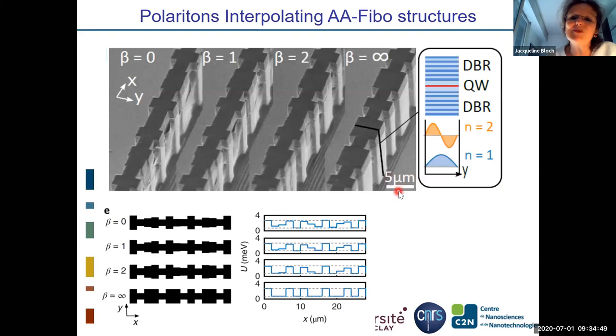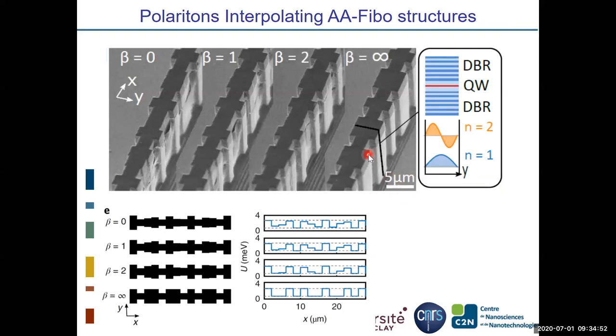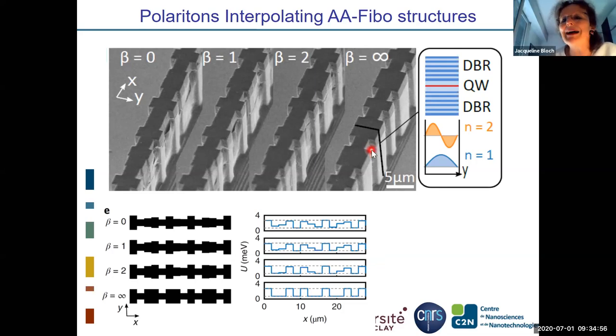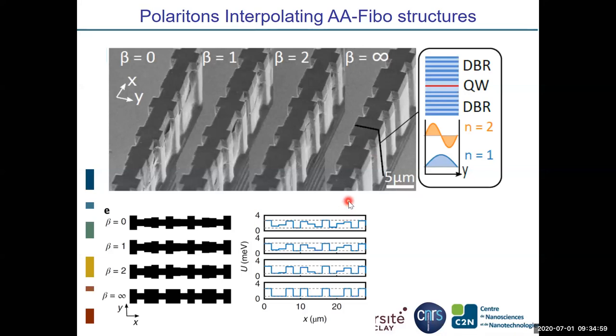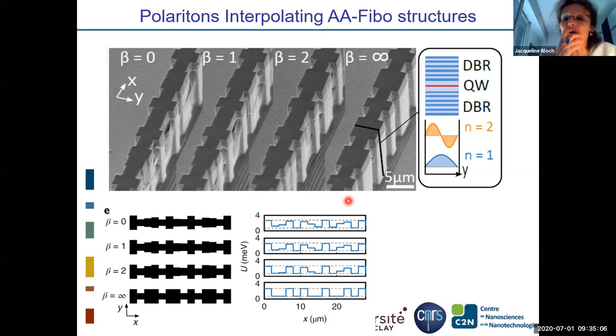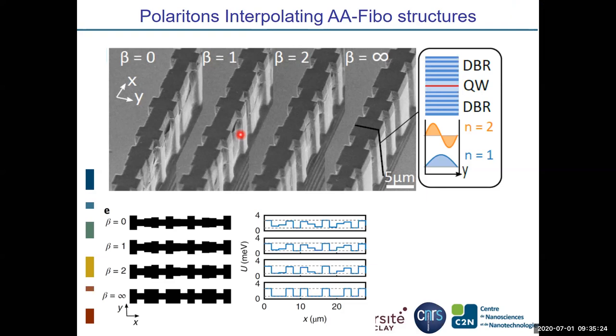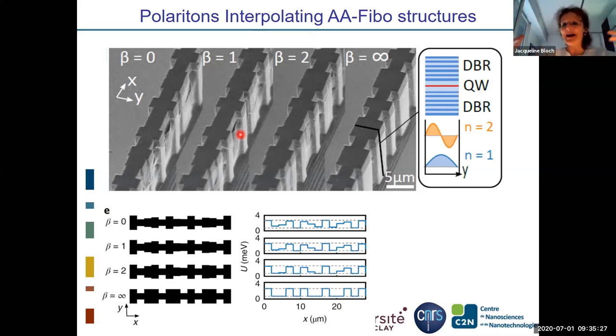Typically, you see, this is 5 micron. I'm sorry, I don't remember the precise number. I think it's of the order of 2 micron or something like this. But is this on the order of the wavelength or less than that? Oh, it's much less. We are around 850, the wavelength inside the material is much, much smaller. But the polaritons, you know, they are big objects. Because of their very light effective mass, a polariton is of the order of 2, 3, 4 micron width, the coherence area. And so they are able to probe a large region of this potential, and so to be sensitive to the periodicity.